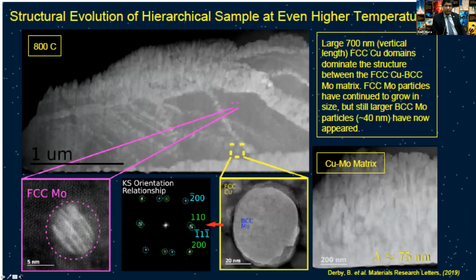If you go even higher to 800 degrees C, which is extremely high temperature for copper, not so much for moly, you'll see again that the structure is maintained. In this case, the structure is getting coarser. The matrix structure is the copper and moly. This is slightly coarser, but there's not much difference. Copper is already FCC from 600 degrees C, and that is maintained here. But inside those copper-rich islands, there are these stringers that are actually arrays of moly precipitates.